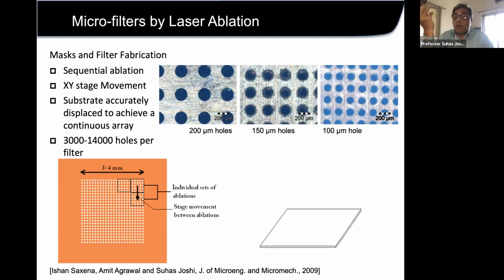If I have 100 micron holes on the mask, I can make those holes of 25 micron, or I can make those holes of 15 micrometers if I have a 1/5 or 1/8 or 1/4 reduction in the optical reduction. And then your mask making becomes simpler because I can make the mask which is bigger, and I can reduce the image of the mask to a smaller extent.